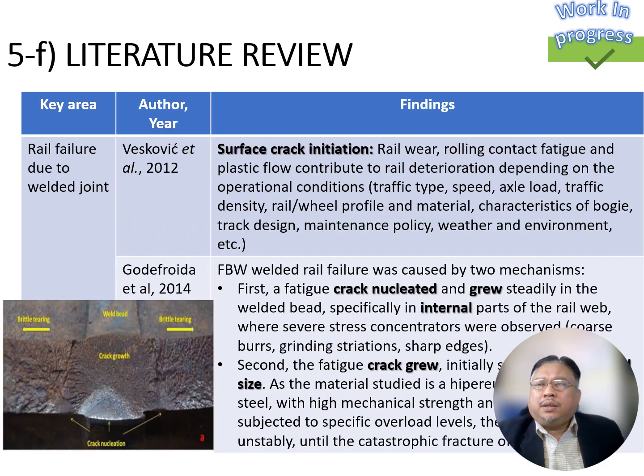Veskovic 2012 outlined that surface cracks happen during rolling contact fatigue and plastic flow due to high stress at a small surface area, which is the contact patch. Furthermore, operation-induced factors such as train speed, axle load, traffic density, and maintenance regime play an important role in the propagation of cracks. According to Godefroida 2014, cracks in weld nucleate in the weld bead, specifically at the rail web, then grow to critical size. Continuous load at this stage will promote the existing crack to grow unstably, which leads to the rail break.